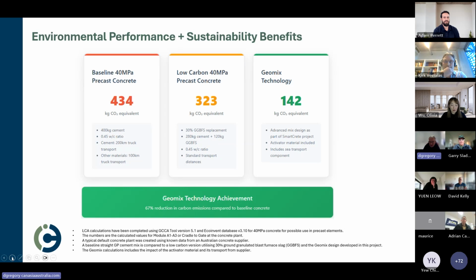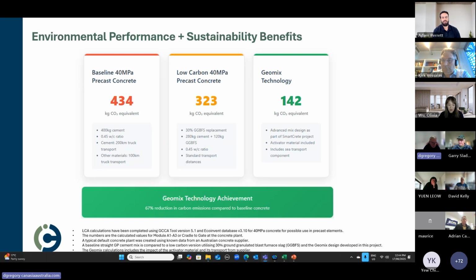This is very dependent on the amount of silicate we use in the mix design. The lower the silicate, the lower this value. We've had a lot of success operating at very low silicate levels, below 1.5% of the total concrete. That gives you a lot of advantages in CO2 emissions, in cost, and in the stickiness of the concrete, which is often associated with geopolymer concrete. We see very similar finishing characteristics when you achieve this low silicate level.